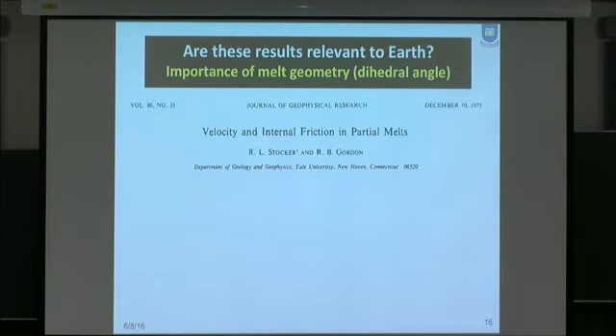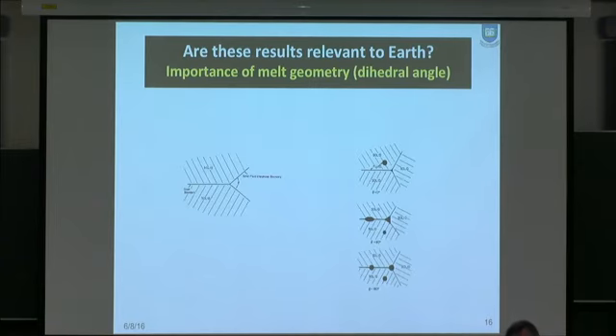However, some 10 years after, a very important paper was published by Stocker and Gordon from Yale University, pointing out that the influence of partial melt, the influence of melt on elastic properties, is extremely sensitive to the geometry of melt. And then they pointed out that you need to characterize what kind of geometry, that is the wetting angle.